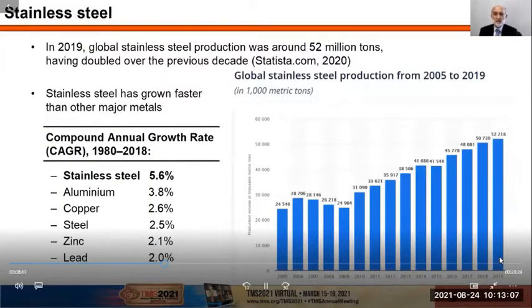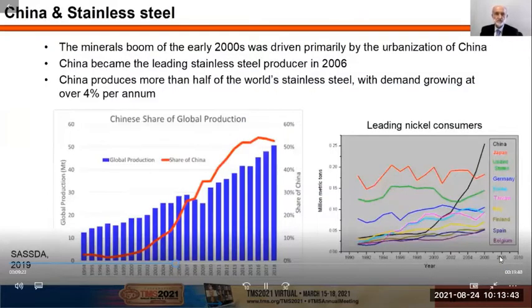Looking now at stainless steel, the ultimate purpose for much of the nickel that is mined, in 2019, global stainless steel production was around 52 million tons, having doubled over the previous decade. Stainless steel has grown faster than other major metals, as can be seen by the compound annual growth rate listed for a number of metals on the bottom left, showing that the growth rate for stainless steel is 5.6% per annum, which really is way in excess of that of other comparable metals.